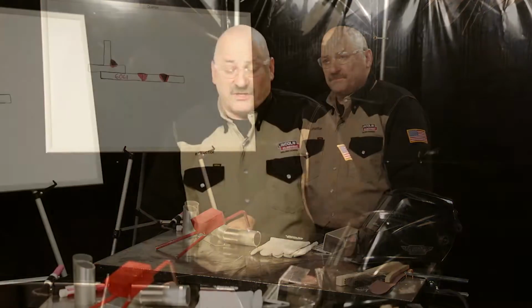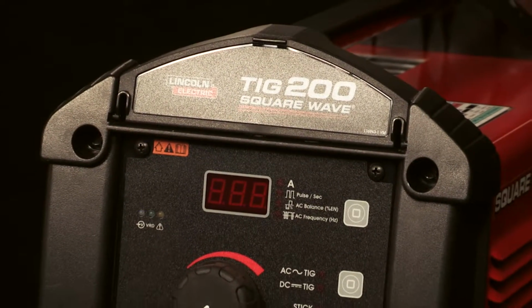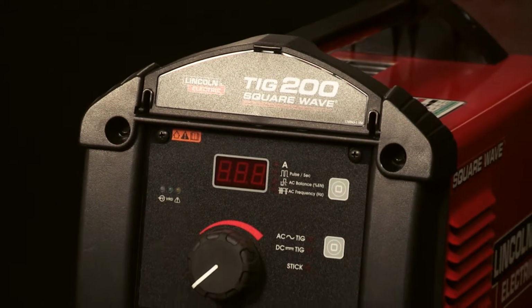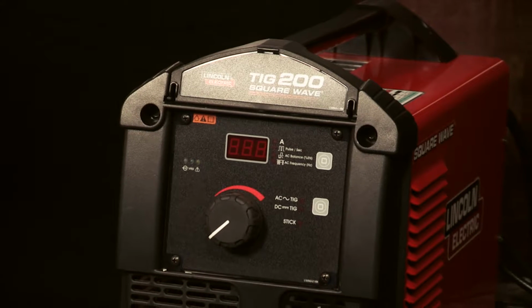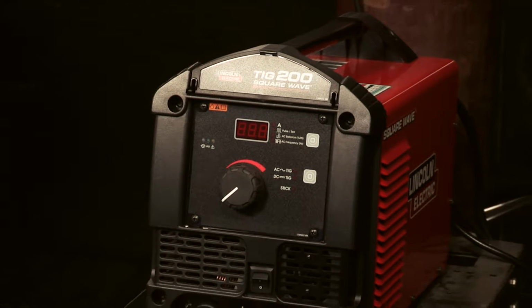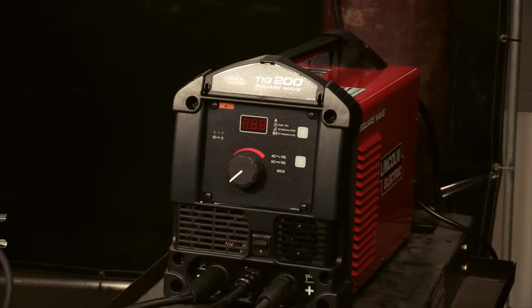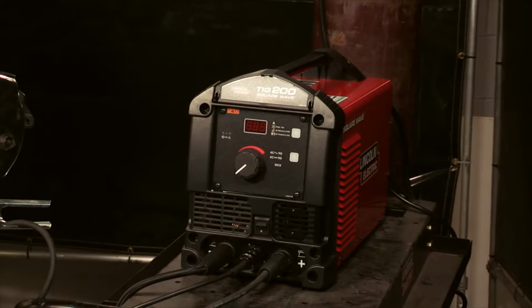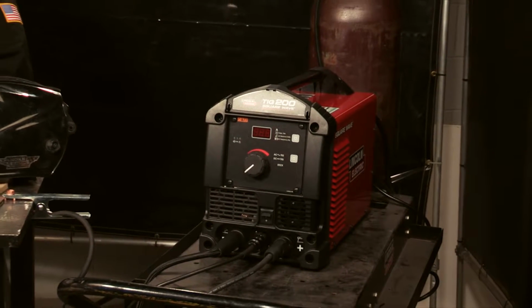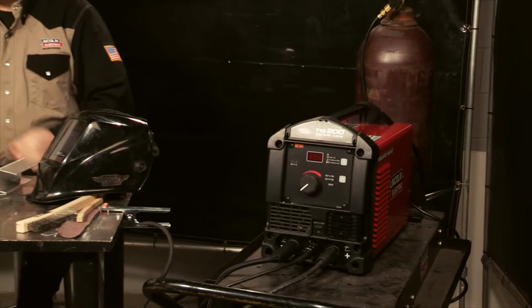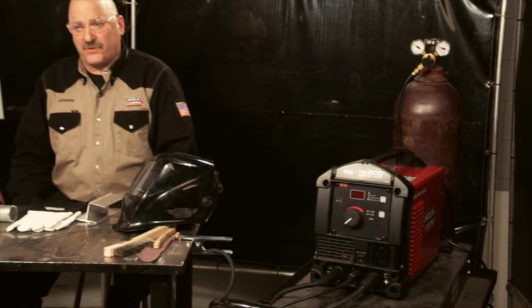these materials. Today we're going to be welding with the new Square Wave TIG 200. And this machine is capable of welding on AC and DC. AC is what we're going to use for aluminum welding today. There's a balance control. It goes up to 85% negative, down to 60% negative. Also has a frequency control where we can adjust the AC frequency from 60 hertz up to 150 hertz.